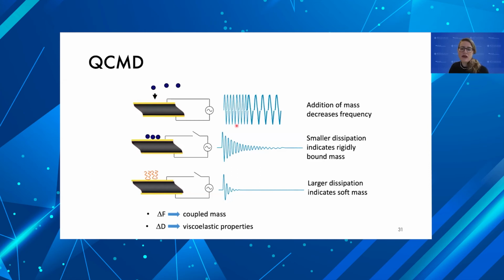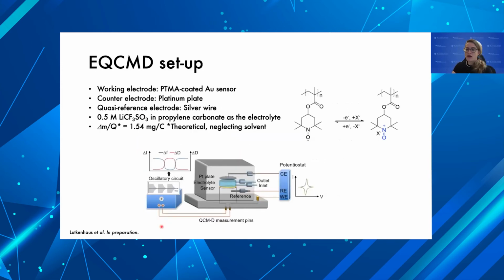With QCMD, for time, I'm not going to go into so much detail of the operation, but our raw data is capturing the coupled mass and the viscoelastic properties during charging and discharging of the polymer by measuring the frequency and the dissipation change of the crystal. So in the setup, we have a 3-electrode cell where the working electrode is the polymer coated on the quartz crystal. And if you're interested in learning how to do this, we've just submitted a review on how to do QCMD for in situ measurements. And I hope that'll come out in a month or two.